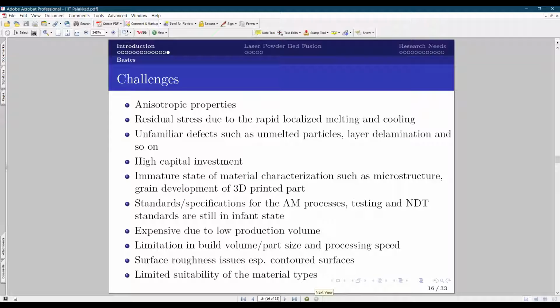Of course, the testing and the NDT standards, both of them are still in an infant state. Let's say if I do a fatigue test on the 3D printed component, the fatigue testing scheme for a 3D printed component is entirely different. Because you have anisotropy, which location you have to take a sample from and how many samples to be taken, this information is not clearly standardized yet. And similarly, for NDT, X-ray radiography or UT is not the best technique to identify the defects in 3D printing. Only very recently people are going for a little more advanced one like X-ray CT, and recently there has been some research in laser ultrasonic methods to characterize the components for defects.